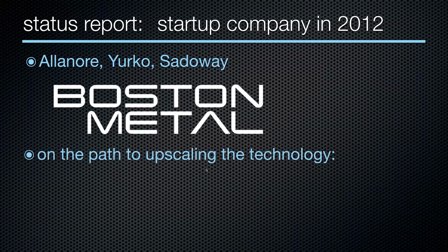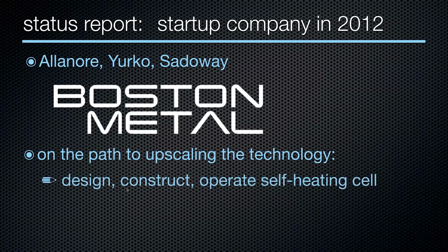And so it's on the path to upscaling the technology, and that involves the design, construction, and operation of a self-heating cell. When I showed you the cell in my lab at MIT, it was externally heated. But just as in aluminum cells in industry, there's only one current. And that current from the anode to the cathode does two things. It drives the Faradaic reactions, making oxygen on the anode and iron on the cathode. But as the current flows through the molten oxide electrolyte, it generates joule heat. And if the cell is properly configured, that joule heat will be enough to keep the cell at operating temperature. There are no external heaters, and so this is quite an achievement.